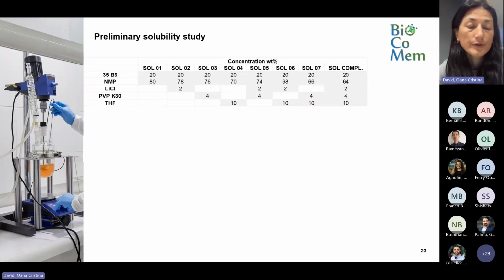This is what we knew already from the literature, and it's an additive we normally use for polybenzimidazole. Then we can have PVP, which is polyvinyl pyrrolidone. It's an additive of low molecular weight, 30,000 grams per mole, that can dissolve in water after spinning when we wash the fibers. It has two purposes: to increase the solution viscosity, so we can form a stable thread, and also, because we can wash it from the coagulated polymer at the end, it can promote pore formation. It can give bigger pores.